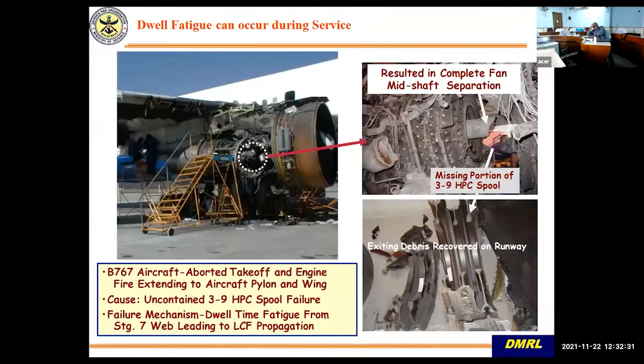Now I will show you the effect of processing and microstructure on dwell fatigue. This is an important new phenomenon, what is called dwell fatigue. I will tell you what is dwell fatigue. You have heard about fatigue, which is just cycling the load. But when you hold a load for a constant period of time at a higher load level, that is what is called a dwell period. And people have realized, because of this dwell effect, there have been cracks which have been generated, and there have been failures which have occurred in engines, and this has been reported. Okay, we will discuss this phenomenon because this is an interesting phenomenon.